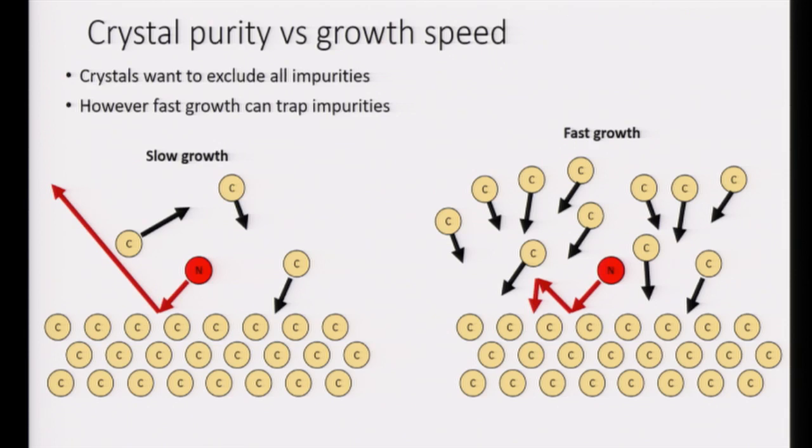Okay, so the process of putting impurities in also leads to defects. And so they're coupled, and that's why you have to decouple. So the idea is to test this for the high pressure growth. We grow slow when the temperature is low. At high temperature, we grow fast because there's a lot more reactive carbon at high temperature than low temperature.